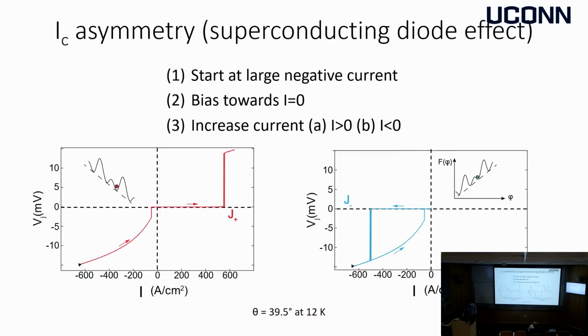So the way this is done experimentally is that you start with a very large current bias, where the junction is no longer can sustain a superconducting current, and then you gradually reduce it. At some point, you go back to the superconducting state. Then you increase the current, and you get to the maximum current that the junction can sustain.